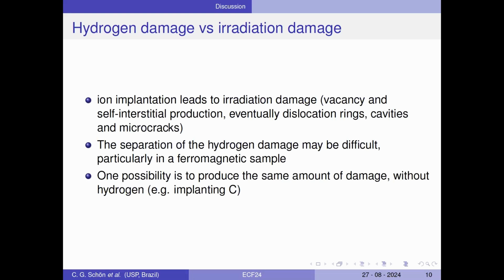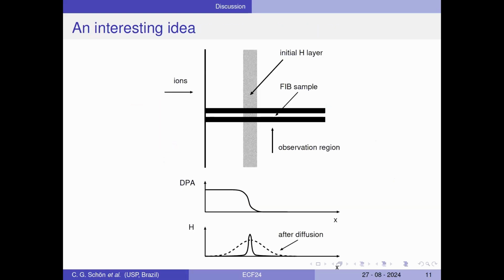One problem that was already identified is that ion implantation produces irradiation damage, and this could produce defects, and we have to separate this. One of the first solutions was to implant something other than hydrogen with the same damage level so that we could identify what is the irradiation damage. But then I remembered something. Imagine that we have an implanted hydrogen layer. So the ions arrive from this side. The damage occurs in the front side of the sample. Hydrogen stops here because it doesn't have enough energy to go further. So the rear side is not damaged, but hydrogen diffuses.